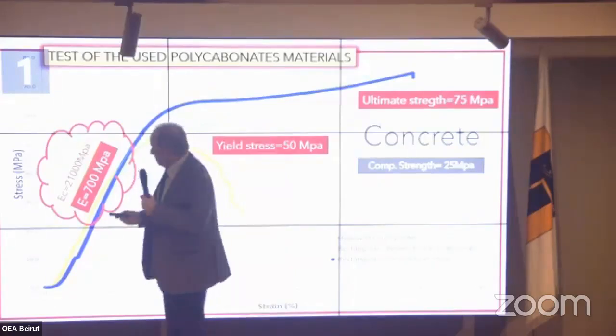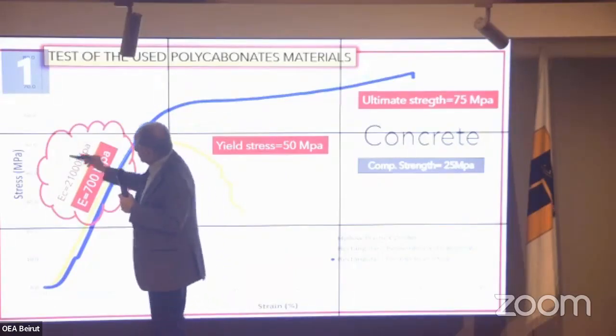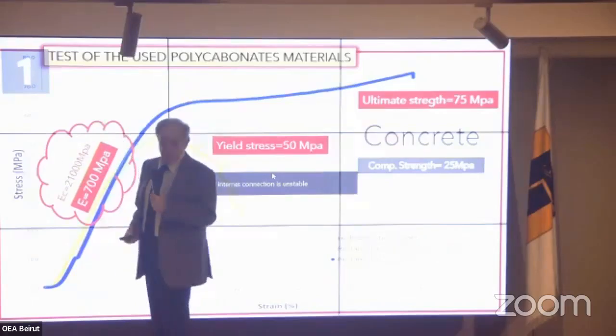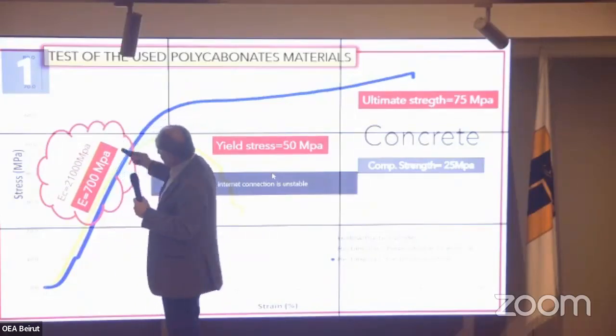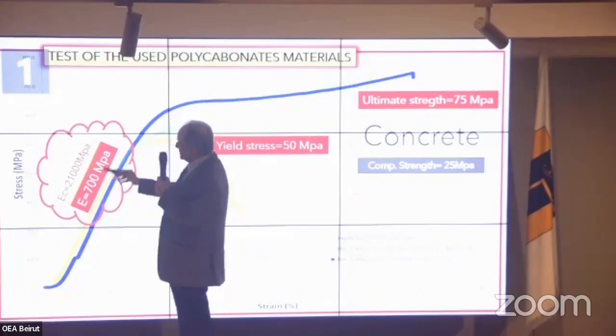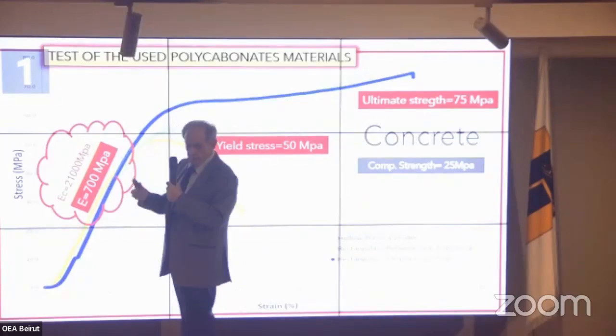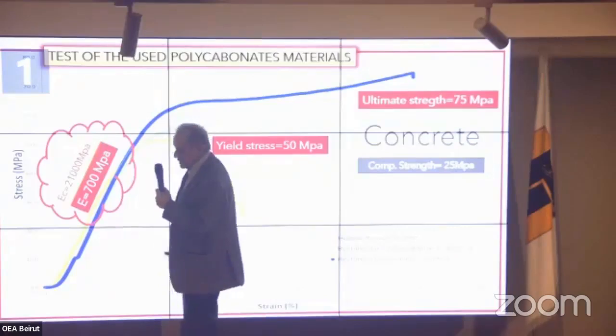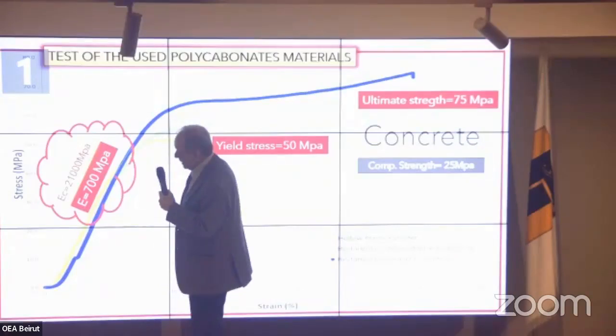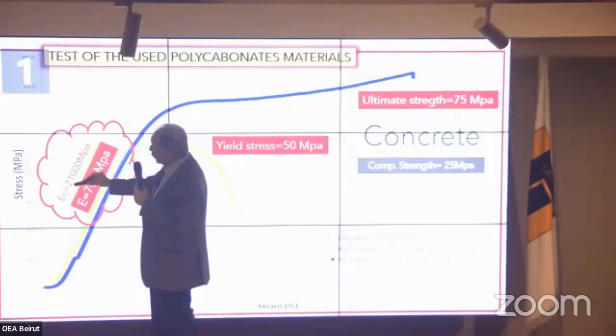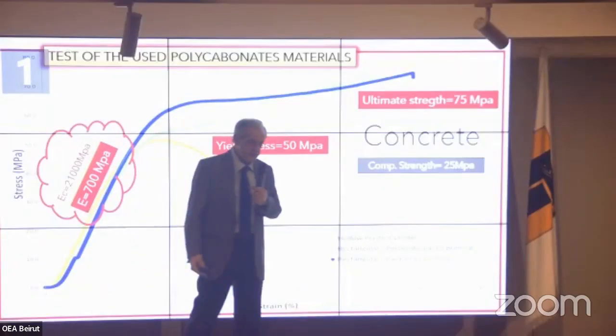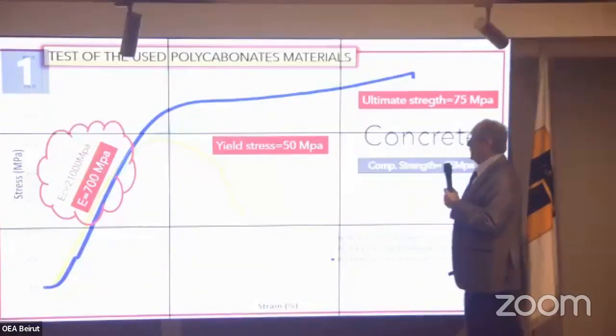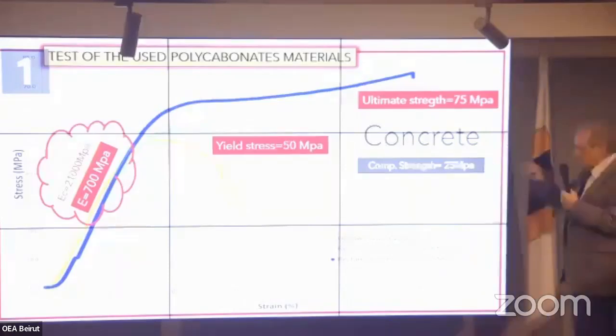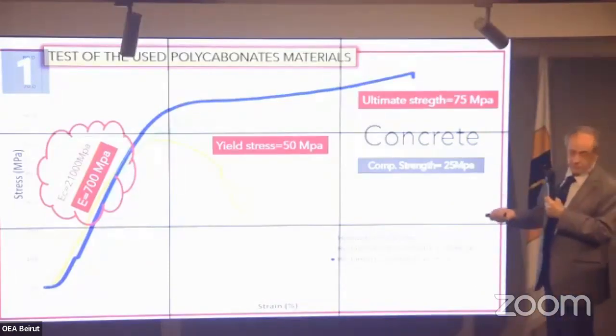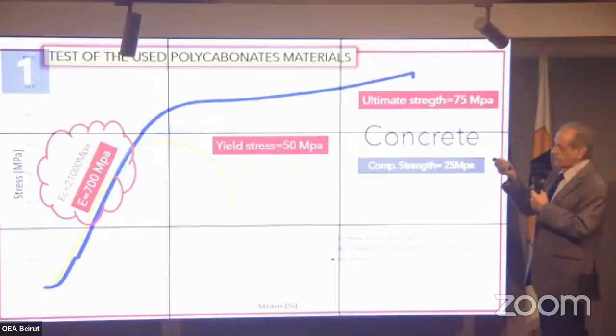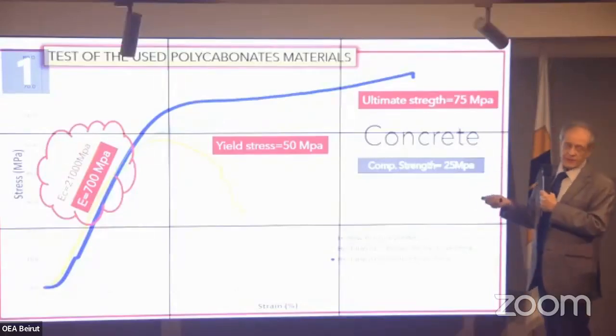You have a problem that the modulus of elasticity is a problem. The modulus of elasticity of polycarbonates was found in our test to be 700 megapascal. That of concrete is around 21,000 megapascal. That's 30 times too much. And this is the problem of plastics. All plastics have the problem of modulus of elasticity, not strength.